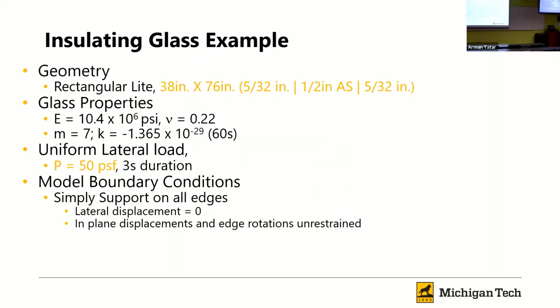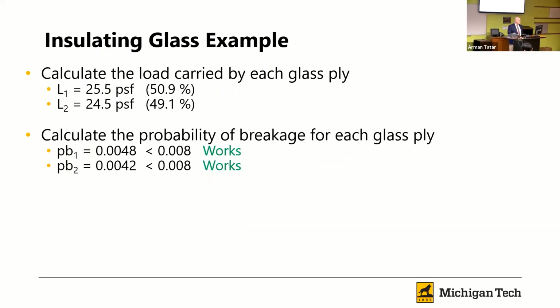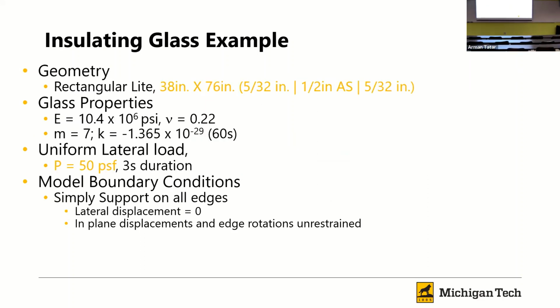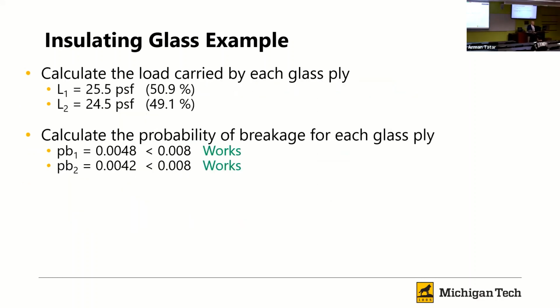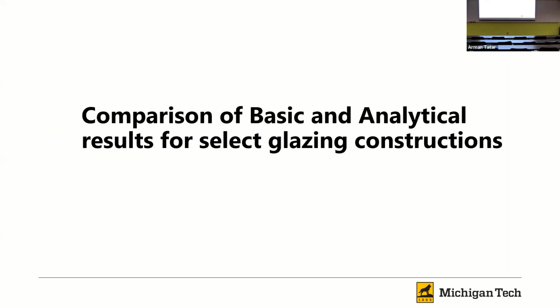Real quick, if I want to do insulating glass, similar process. And in this case, we chose a 5/32 inch with a 1/2 inch airspace, and calculated our load share between the two of them. Notice that those were close to 50%, but they were a little bit off. In other words, the loaded light's going to carry a little bit more because there's a little bit of squishiness in our airspace. We don't transfer all that because we have a compressible gas in there. And so in this case, that design worked.